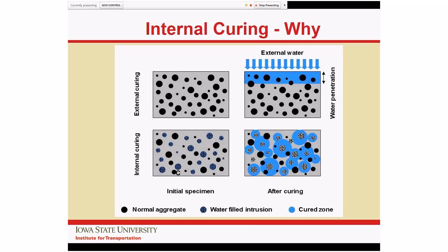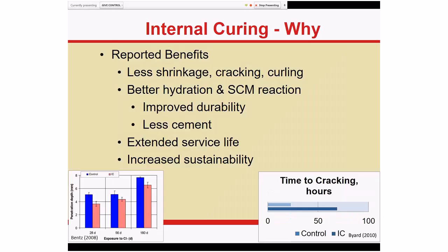Internal curing, on the other hand, is where we basically trap little spheres of something that contains the water. And then as the water is allowed to escape back into the mixture, you can see that the blue area where the curing has been beneficial is now pretty uniformly distributed through the whole thickness of the specimen. It's a whole lot more blue than in the top right-hand image. And so we're getting rid of the differential. We're also encouraging curing throughout the specimen, and so, also in this case, throughout the bridge deck. So we're getting improved performance throughout the system. And so, theoretically, it sounds like a really good idea.